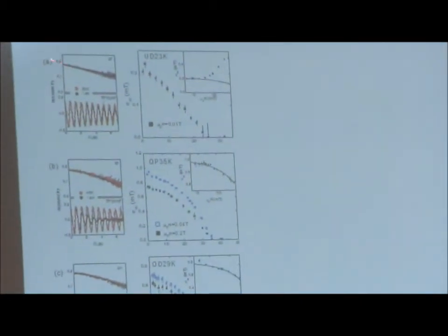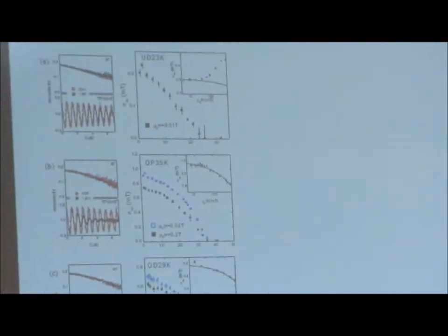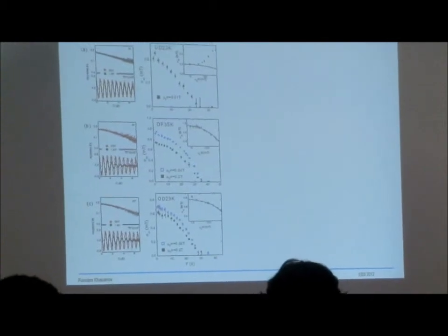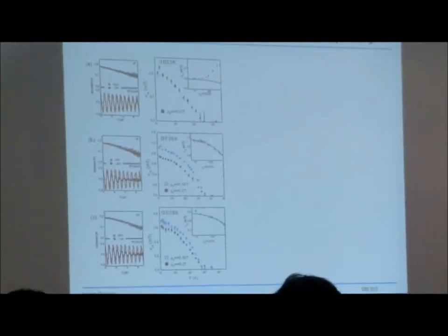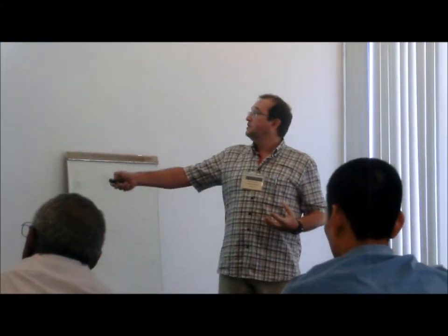What is really important is that all of our samples are non-magnetic, because the zero field spectra above Tc and below Tc are just the same. There is no magnetism appearing as soon as we pull down the superconducting transition. What is also clearly seen is that as soon as we go below Tc, we have additional damping, which is caused by the appearance of the vortex lines. As I told you before, this is an indication of the vortex lines, from which we could obtain the width of this distribution, plotted here.